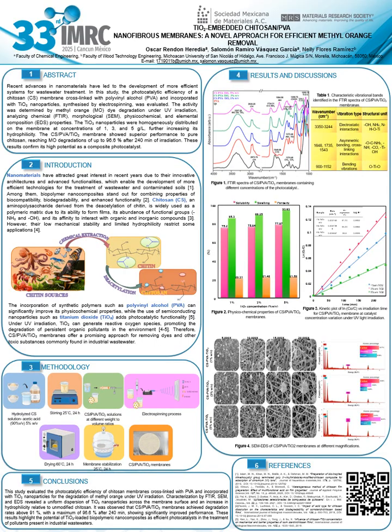About the energy dispersive X-ray spectroscopy, it confirmed the homogeneous distribution of titanium throughout the membranes, as evidenced by strong titanium signals overlapping with the polymeric matrix. This uniform dispersion is crucial for exerting consistent photocatalytic activity across the entire surface of the membrane. Compared with pure chitosan or other conventional membranes reported in the literature, the chitosan PVA titanium dioxide nanofibrous membranes exhibit superior removal efficiency, faster kinetics, and improved mechanical stability. These findings underscore the potential of electrospun polymeric composites as multifunctional materials for advanced water treatment.